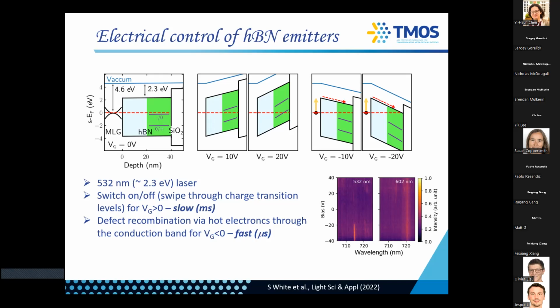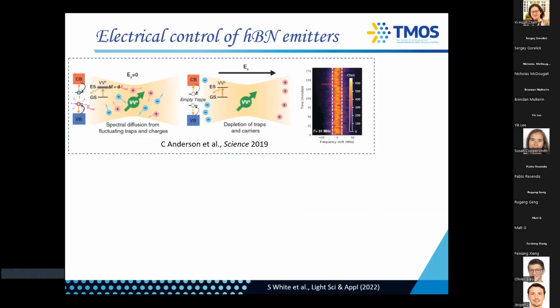Now, why did I waste your time telling you all that? If you look back in the literature, in silicon carbide, for example, this is the work from the group of David Awschalom. They create PIN junctions in silicon carbide and apply negative bias. Under negative bias, they create a depletion layer, and when you have a depletion layer around your defect, there are no fluctuating charges. Remember, the goal of the whole exercise was to eliminate these fluctuating charges. We were just hoping to do it by a bias alone, but it didn't work.